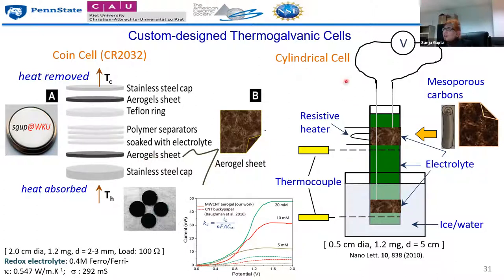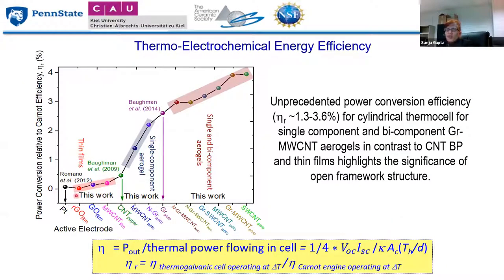The other configuration is basically a simulation of what I showed you before, the cylindrical cell, where you have a hot end, which is through a resistive heater, and then this is placed in basically ice cold water for the cold end. And what we obtained, I'm just showing you the efficiency right now, and we compared with platinum, which is the classic material.